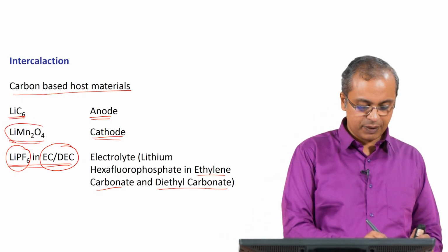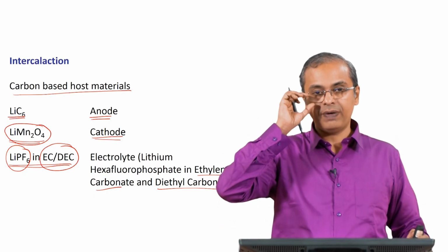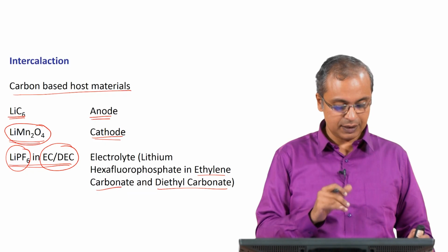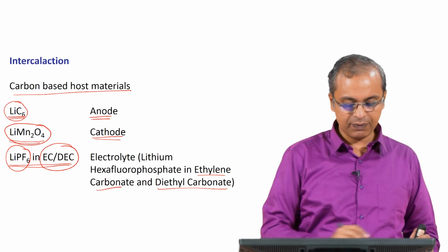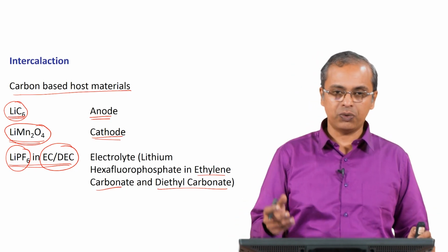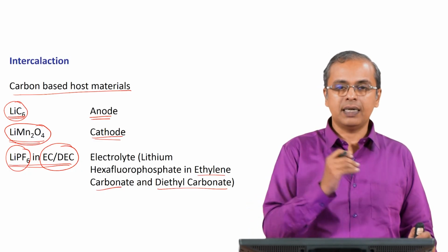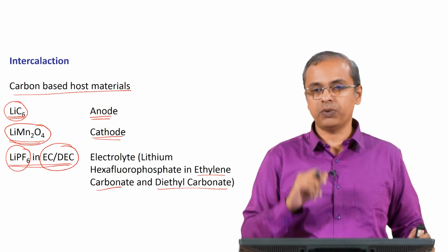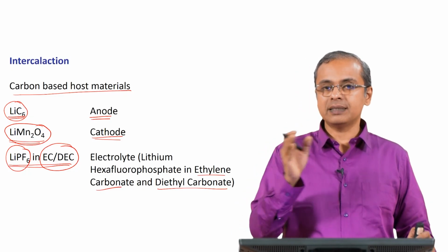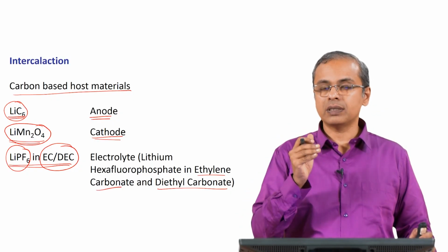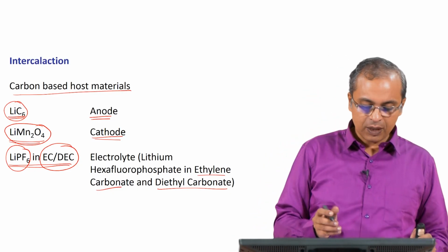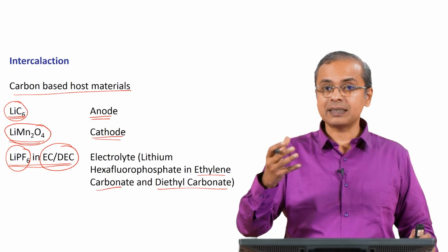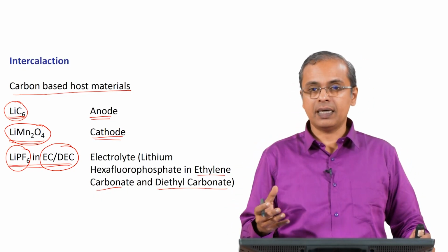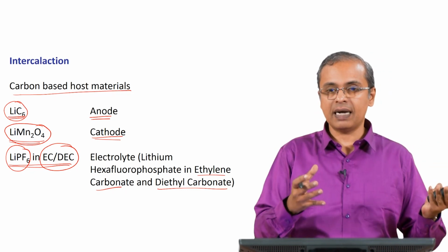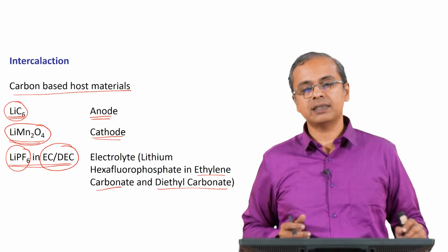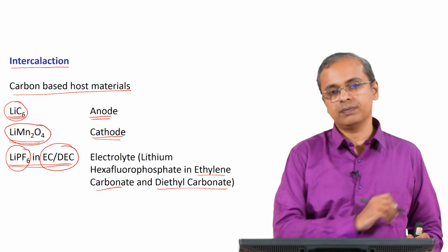Lithium manganate, many other cathode materials have also been investigated, primarily with the intention of having a high voltage window between lithium and carbon and this lithium manganate, and another set of host materials are being investigated for the anode, which are mostly carbon based. So, they are looking at nanotubes, they are looking at graphene, various different carbon based sources which can hold the lithium at a potential very close to lithium metal. So, you are not losing the potential of the lithium metal, but you are not keeping it as lithium metal. So, the plating stripping process is not there, and therefore, this dendritic growth is not an issue and short circuit is not an issue. So, this is the idea that you will keep the lithium inside a host material, and given the structure of graphite, which is a layered structure, this keeping of lithium inside this layered structure of graphite is referred to as intercalation. That is this term called intercalation.